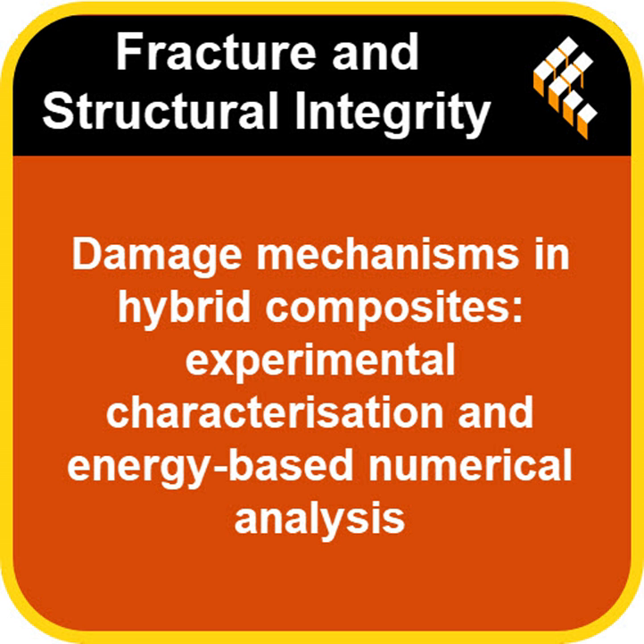Absolutely. They confirmed that damage within the layers, that intralaminar damage, is the primary way these materials fail. It dissipates the most energy, followed by the layers peeling apart, the delamination. Okay, primary and secondary mechanisms. And crucially, less intralaminar damage builds up before the peak force when you have glass on the compression side. Delamination generally starts happening around the point of peak force. It's more significant in pure carbon and barely happens at all in pure glass.